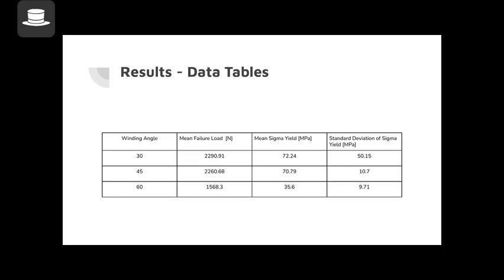Our 45-degree winding angle tube was the middle strength value, which was expected based on our hypothesis, with a mean failure load of 2260 newtons and a mean sigma yield of 70.79 megapascals. This tube had a better standard deviation of approximately 10.7 megapascals, which would further be reduced by adding more data